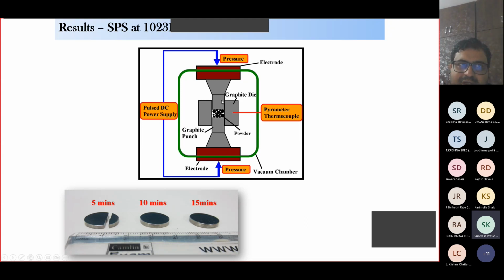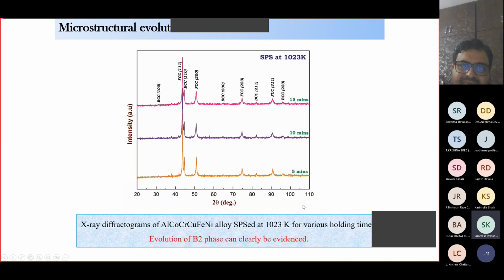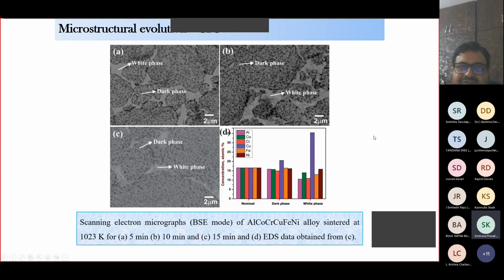We did that using spark plasma sintering using the facility in ARCI, Hyderabad, and these are the samples. You see such a nice sample. We cut them for further calculations. So such a bulk sample we have. And after spark plasma sintering, interestingly, you see a phase transformation. You see a new phase that is an ordered BCC structure in addition to the parent FCC structure. So eventually you develop a two-phase structure, which is something that you want for all engineering applications.